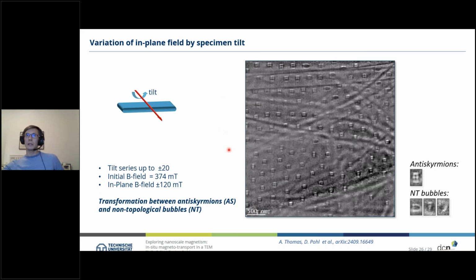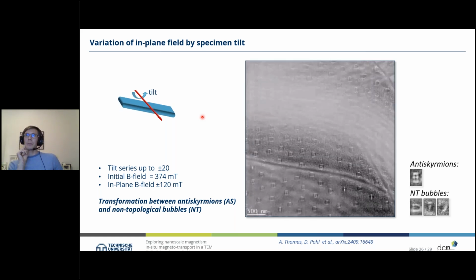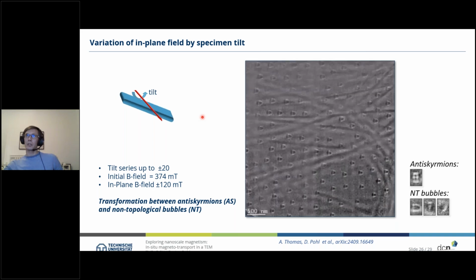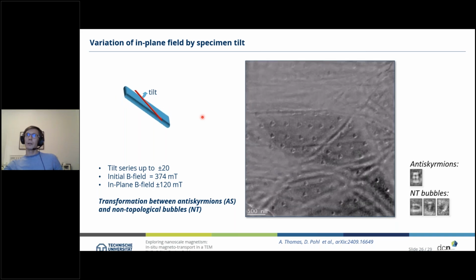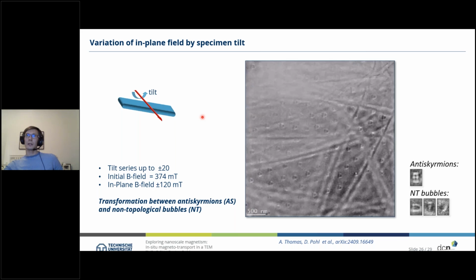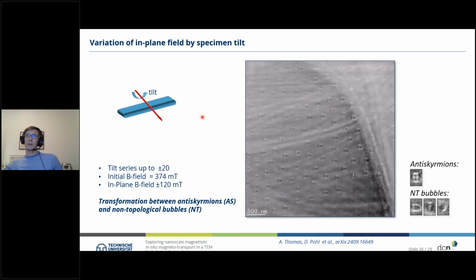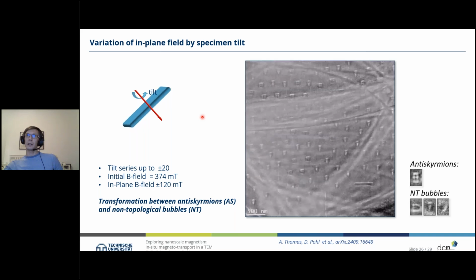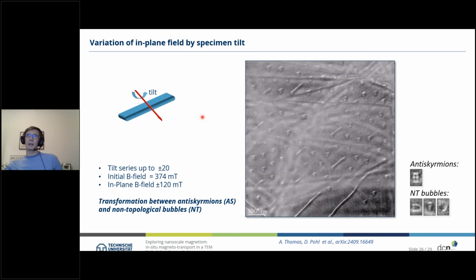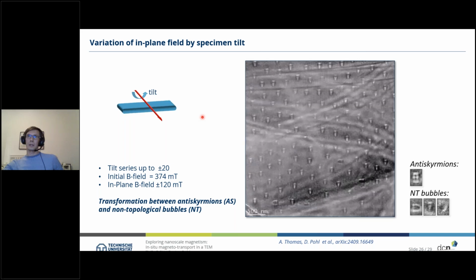But what you can also see is that we will lose at some points the anti-skyrmions. We will see the appearance of some non-topological bubbles, and then transform them back to anti-skyrmions when we tilt back. So we are tilting up to 20 degrees. You see now we only have non-topological bubbles. And then tilting back, at some point, the anti-skyrmions will pop up again because we reach the correct in-plane magnetic field. Here the anti-skyrmions pop up again. Some non-topological bubbles pop up again, and then we come back to the untilted starting stage.